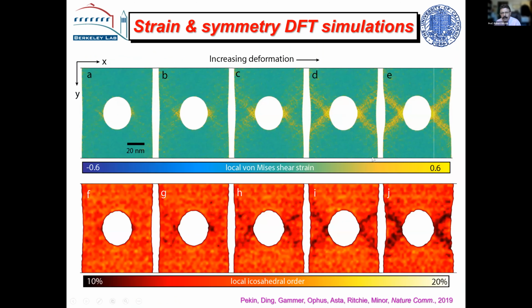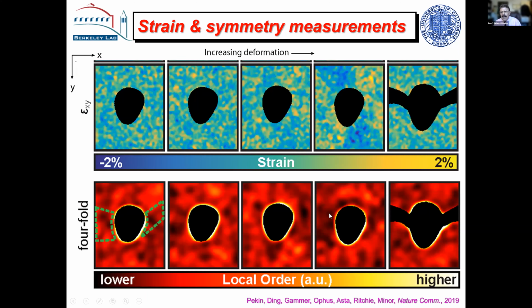And you can see the predictions first. This is the predictions of where the shear bands are forming, and of course they're forming where you'd expect. We're loading it, you know, in the vertical direction here. But if we look at the regions of local icosahedral ordering, that means where the GUMs are the greatest, they form in the same bands. So it does seem to be a tie-up between shear banding and these GUMs. Now, this is a prediction. We tried to look at it in the microscope. This is not as clear, but I think you can convince yourself that you can see the regions of strain again at 45 degrees or nominally 45 degrees.